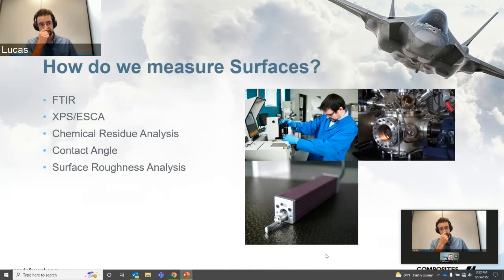The other thing that you do need to worry about with treatment is you can create reactive sites on the surface, but they can reorient down into the bulk. Now, to Lou's point, that's thermoplastic specifically. But it's something to keep in mind, right? The point here is that these things are sensitive. It's a super thin region and it's mobile. Things are changing all the time, right? So a surface that we care about for these applications is quite thin. It's invisible to the naked eye. Surface energy gives us a way to start describing how these things move around or how they change as we do preparation to them or cleaning.